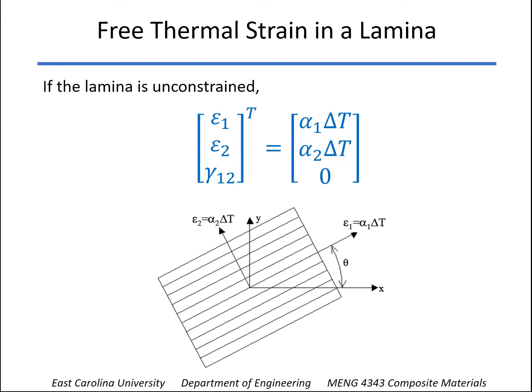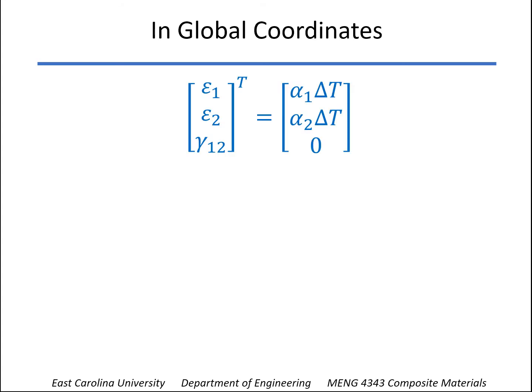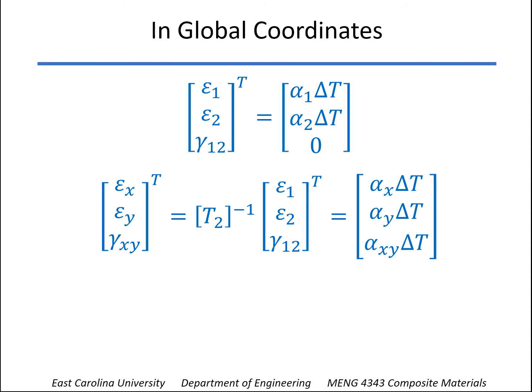And so we get these free thermal strains. The superscript T just means free thermal strains: the thermal coefficient times delta T in the fiber direction and in the transverse direction. And again, if we're totally unconstrained, it's not going to warp or shear one way or the other, so gamma 1,2 would be equal to 0 here. But we need to transform those into global coordinates. As with any strains, we can use the T2 inverse matrix to transform those. And so the new free thermal strains on the right would be related to our thermal coefficients alpha x, alpha y, and alpha xy in global coordinates. Each of those times delta T would give us the free thermal strains in the global coordinates.